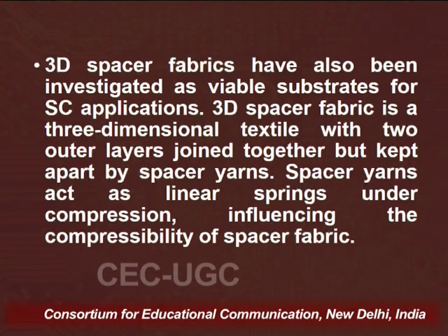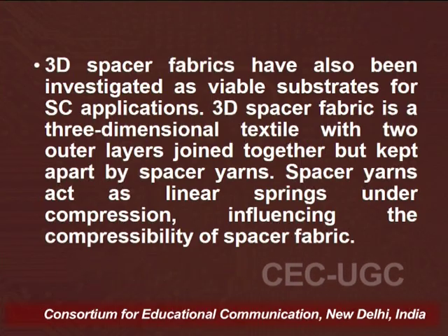Moreover, on the other hand, synthetic textiles typically possess low surface energy, making it difficult for conductive materials like carbon nanotubes, graphene and conductive polymers to adhere without surface modification or chemical treatment, which can compromise flexibility or add toxic components. Another option is the 3D spacer fabric, which has also been investigated as a viable substrate for supercapacitor